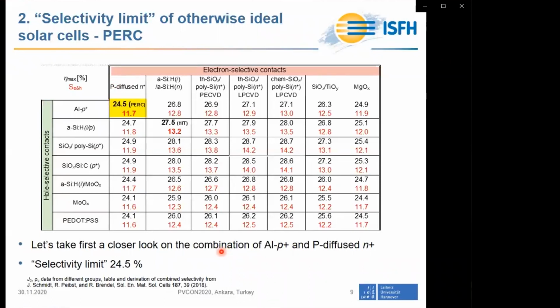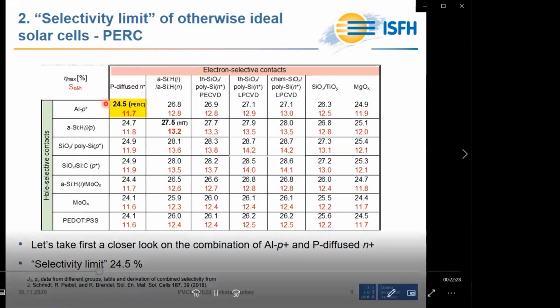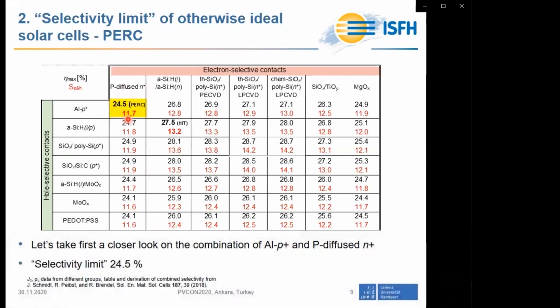The industrial most relevant case is the combination of a phosphorus diffused n-type emitter with local aluminum p+ hole collecting contacts, because this combination is implied in the so-called PERC cell, which is the workhorse of today's PV. For this combination, we calculated a combined selectivity of 11.7 and a resulting efficiency limit of 24.5% for the given J0 and ρC data as specified in this work.